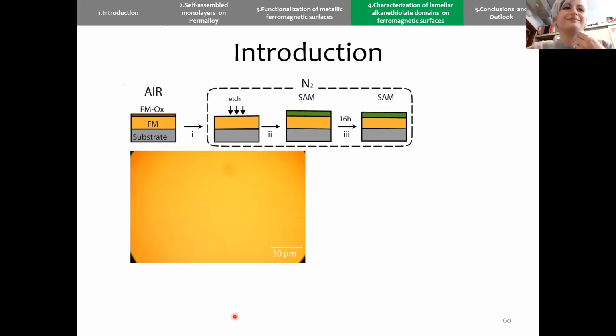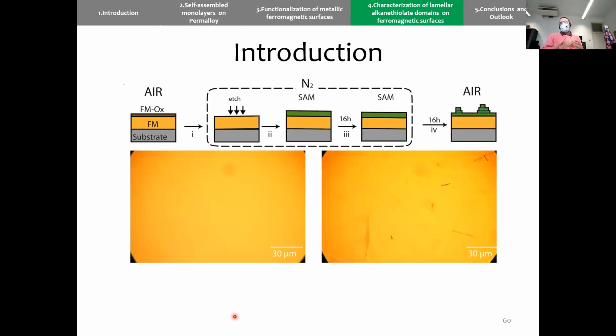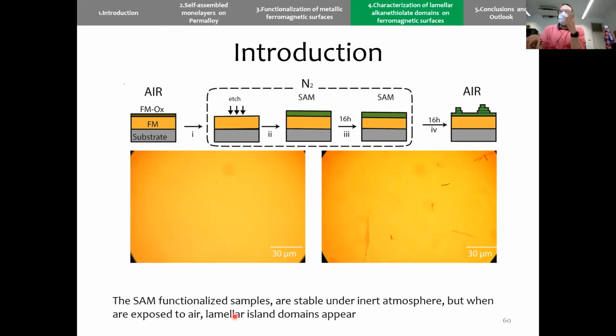Okay. So what we have observed until now: if we do this process in a glove box, the surface is smooth, but the moment we expose this substrate with this surface to the air, we observe lamellar domains. And first we started thinking about contamination, then we checked everything twice. We checked the purity of the substrate, the purity of the solutions, and we were not capable of identifying the problem.